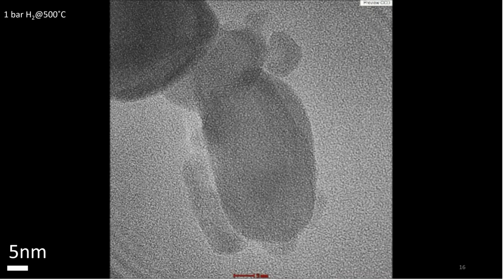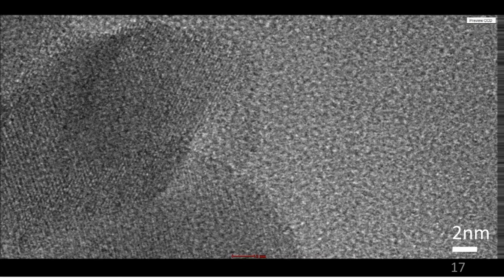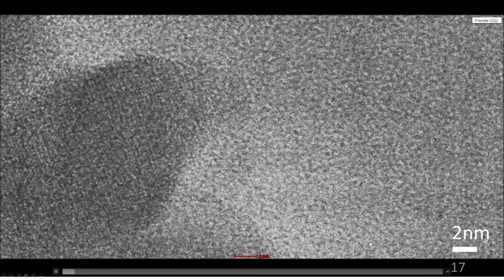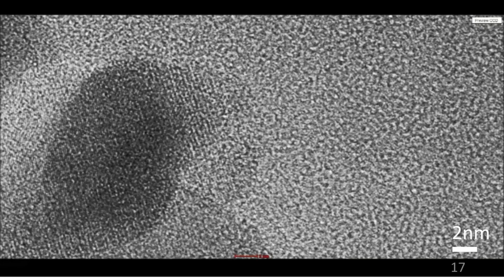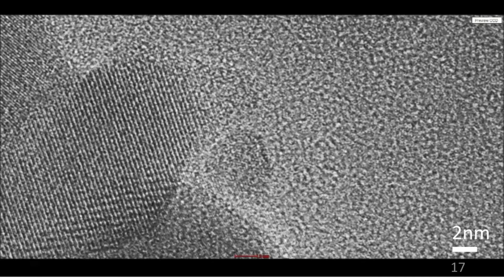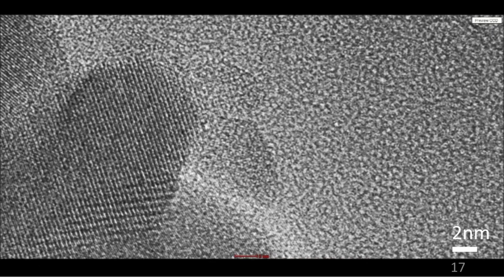And during the reduction process, we can see the nucleation of the magnetite happened at the corner. It means that the new species of the iron oxide migrate from the parent particle to the corner and form the new particle with a different crystalline structure.